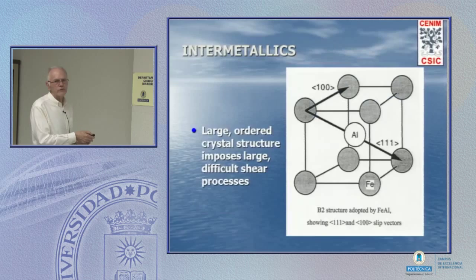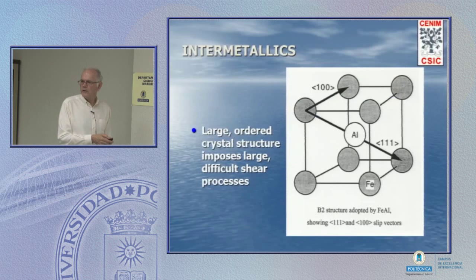Now if we look at the crystal structure, here's the BCC crystal structure, which you would find of iron, of steel. In that case, each atom would have the same identity. And this vector from the corner to the center, the half 1, 1, 1, is the easiest vector of shifting. That's the vector of the dislocation that carries out deformation. Now in the ordered cell, we've got iron on the corners, aluminium in the center. A half 1, 1, 1 vector takes a black atom to a white site. It disorders. And the crystal doesn't like that. It likes to stay ordered.